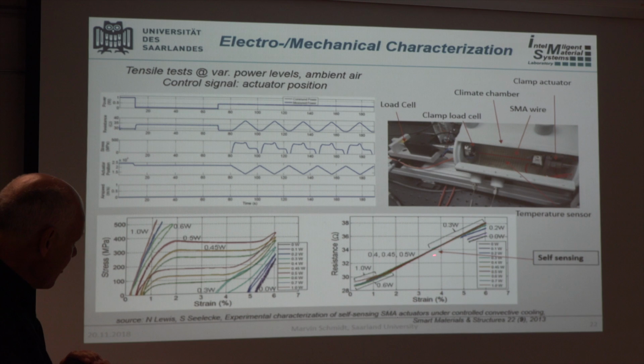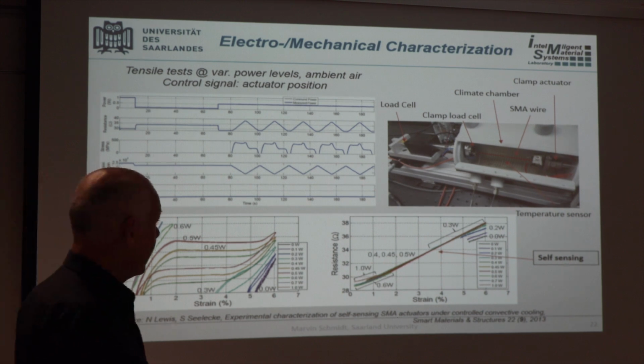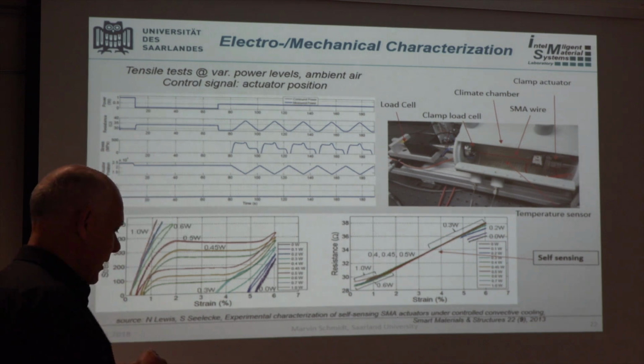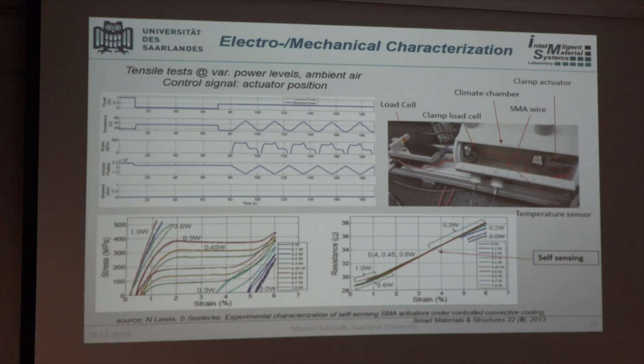And so the other interesting observation that we make is that the strongly hysteretic behavior that we see in the mechanical picture is completely gone. So when we measure 34 ohms, I can read off and I know the wire underwent 3.6-some % of strain. And this is regardless of whether I'm here, here, here, here, here, or here. So I can use the resistance reading from a simple wire as a position sensor. And I can set up a mechanism, again, where I lift weight and I can control it without external sensors by building closed loop feedback loops here, and have basically a very compact system that provides a lot of energy and work output and also provides its own sensing mechanism.